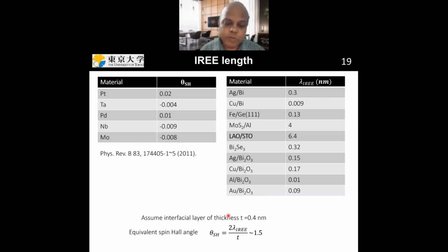So if you assume the interfacial thickness is around 0.4 nanometer in the case of the silver-bismuth interface, then you can calculate the equivalent spin Hall angle to be around 1.5, which is very, very large compared to any heavy metal we know so far. So that's why the Rashba-Edelstein effect is much more efficient for spin charge conversion compared to the spin Hall effect. So that's why people are looking for many different kinds of Rashba interfaces to study.